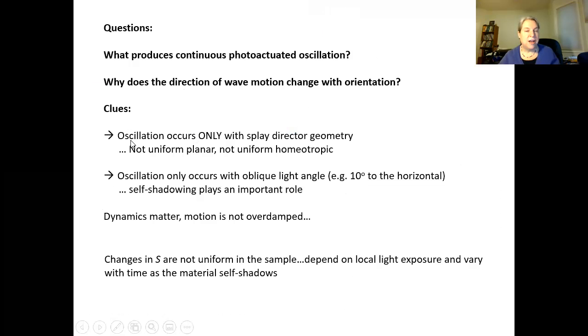The oscillation only occurs if there's a splay geometry in the sample. They tried uniform planar, they tried uniform homeotropic, no oscillation. They only see oscillation if they have an oblique light angle, 10 degrees to the horizontal. So shadowing is clearly involved. The dynamics matter, and the motion is not overdamped. The changes in S, the scalar order parameter, how nematic the system is, are not uniform in the sample. They depend locally on the light exposure and vary with time.